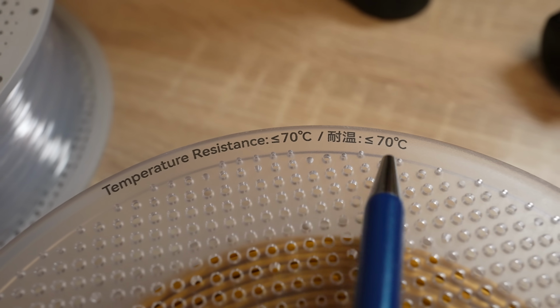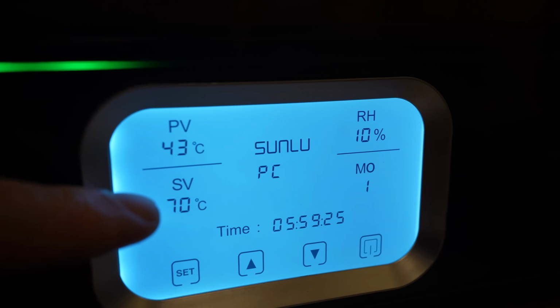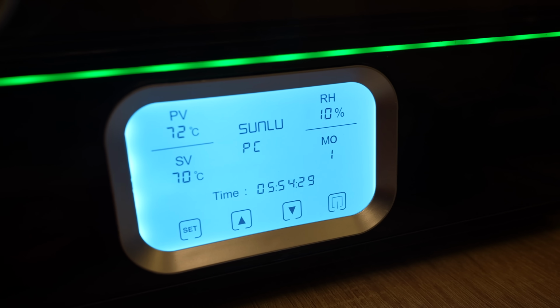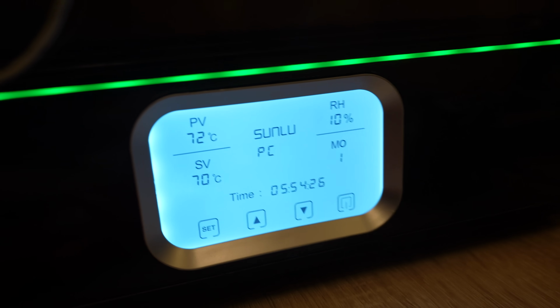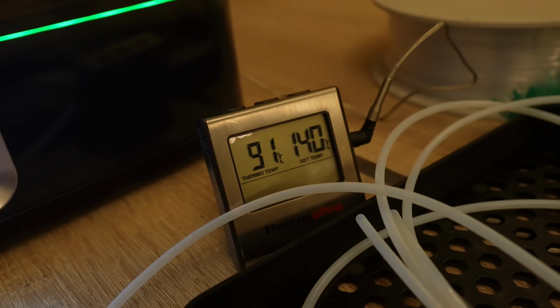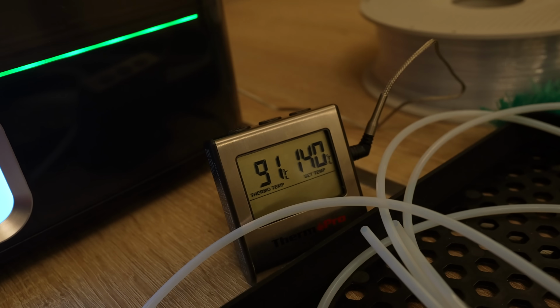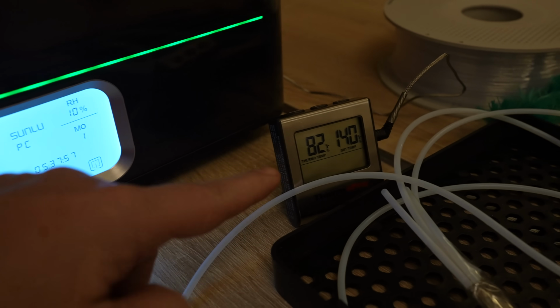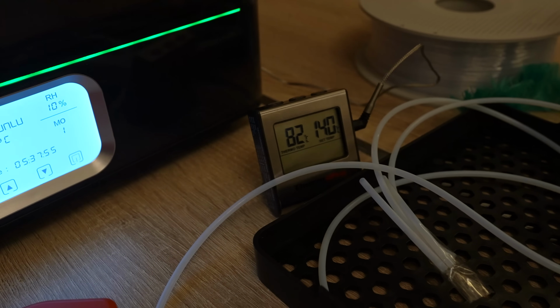And now let's see what happens if we set the temperature to 70 degrees Celsius. It reached 70 degrees Celsius in a little bit more than 5 minutes, but the temperature of the hot air was 91 degrees Celsius. Looks like the air temperature stabilized, and let's analyze the data.